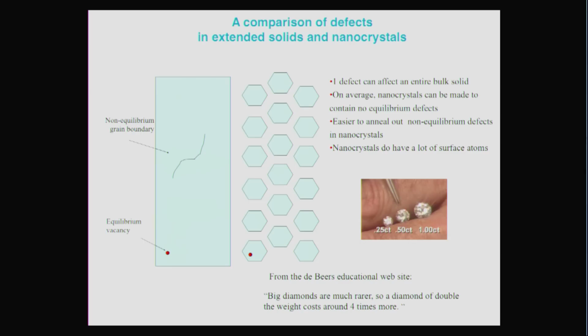Where does that come from? That comes from the fact that to make a perfect crystal requires annealing out of defects. And the time to anneal out a defect will scale exponentially with the volume of a material. So if the crystal becomes quite large, the probability that any defects that might have been there when it was initially forming will be very, very long the larger the crystal, and therefore it will become a much more rare material, and therefore much more expensive.